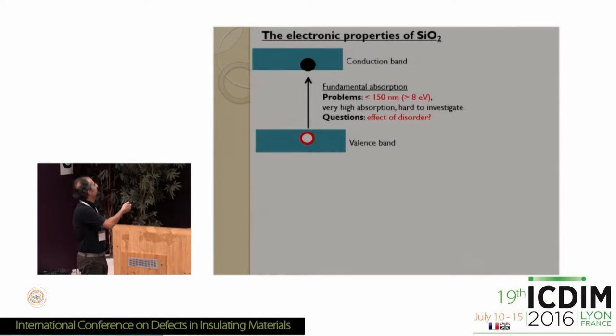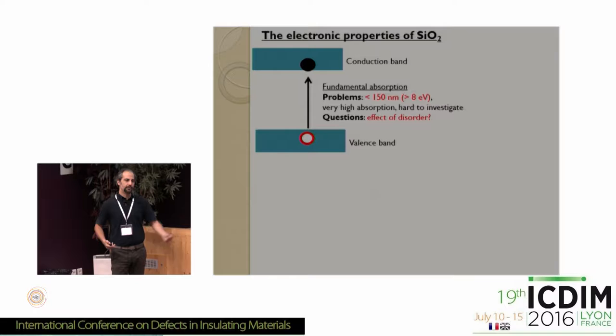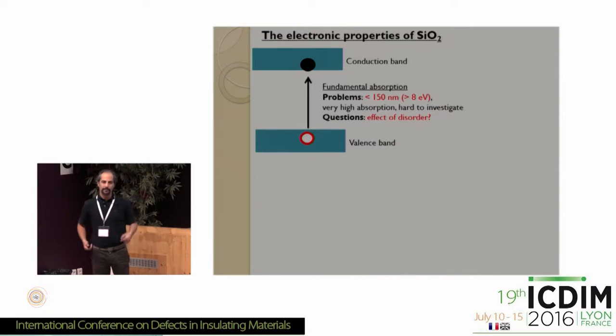Okay? Now, it's not so easy to study in a direct way the fundamental absorption edge of a material because, first of all, the absorption coefficients are very high unless you use a very, very thin specimen. And in the case of silica, which is a very wide bandgap material, this fundamental absorption edge falls at very short wavelength. So it's not easy to address directly this kind of problem by normal spectrophotometric measurements. So we'll discuss later how it's possible to attack this question.